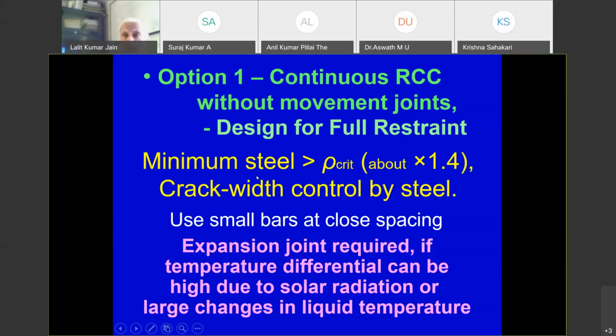If the concrete has high shear, high shrinkage, the critical steel will be high and so on. So in option one, I can give you a thumb rule. It's not written in the report. I give you, your steel has to be more than 1.4 times. If you go for 45 to 50 meters, your steel will be more than double the rho critical. But most of the time, I can say that it is more than 1.4 times.